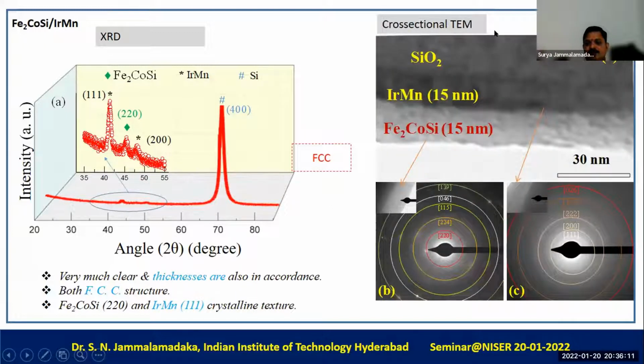This is a cross-sectional TEM that we have obtained. There is a clear distinction between the various layers, and the SAED pattern confirms that this layer is the Fe2CoSi layer, and this layer is the iridium manganese layer. This has been confirmed based on the HKL values that we obtained from the SAED pattern.